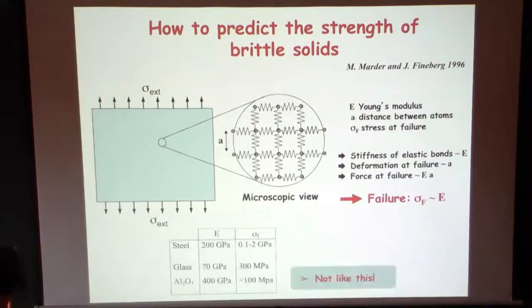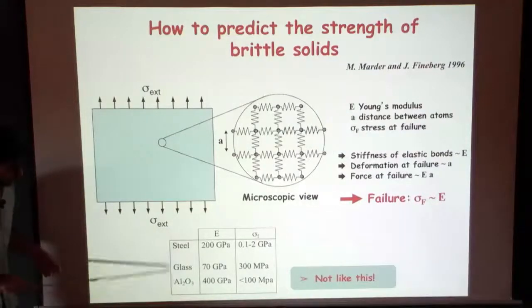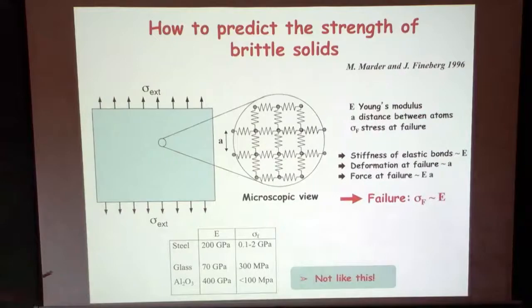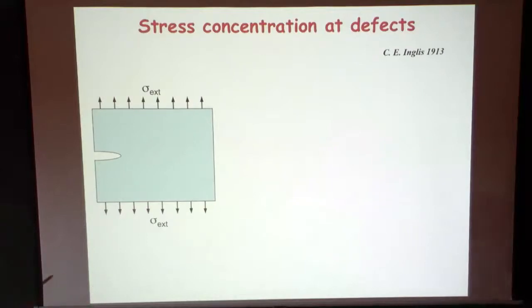And this prediction is actually quite bad: if you take typical materials, it is off by about two orders of magnitude. You predict a strength that is much larger than the actual strength of material. Strengths are weaker, so the failure occurs much before. This is a kind of theoretical strength that can be achieved only in some ideal situation, a flawless material, but it's not at all the general case. And to go a step further in the understanding of fracture, you need to introduce defects, which will be key in the process of fracture.